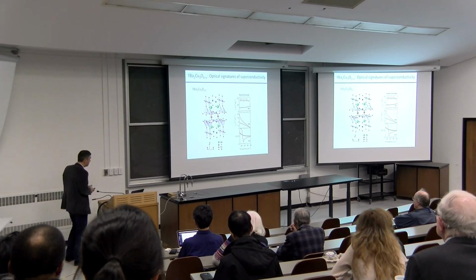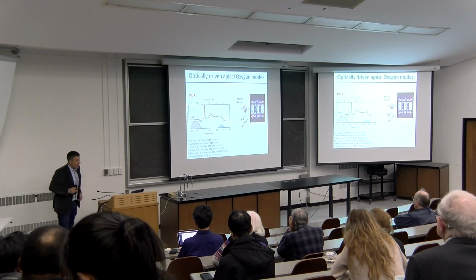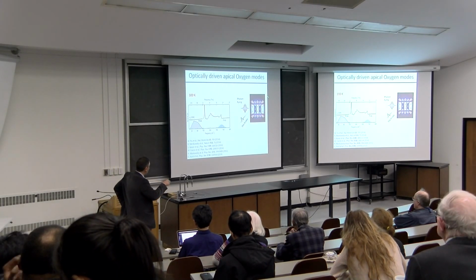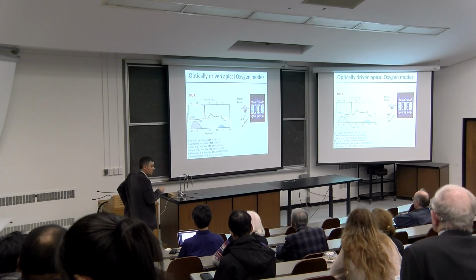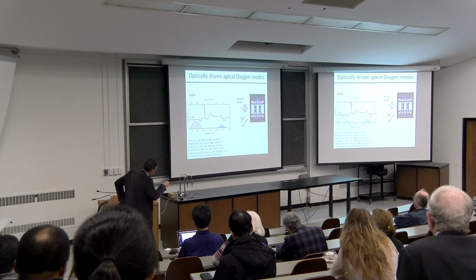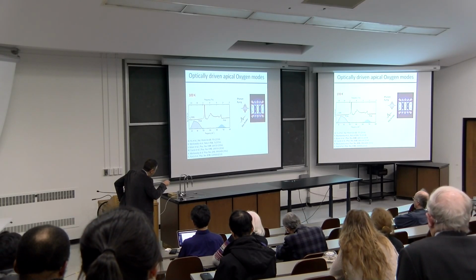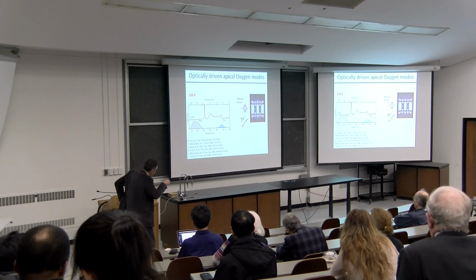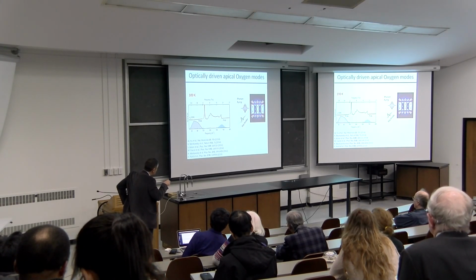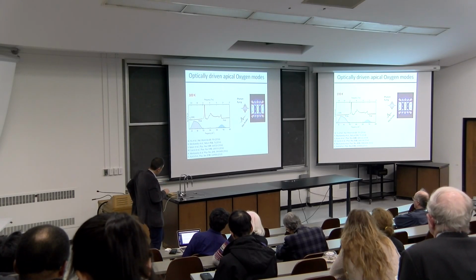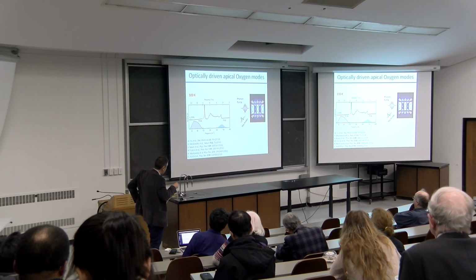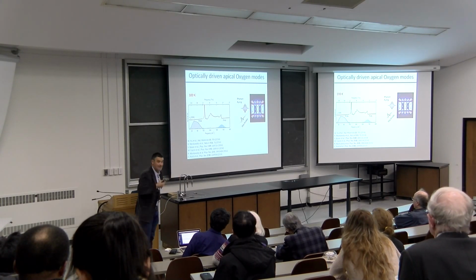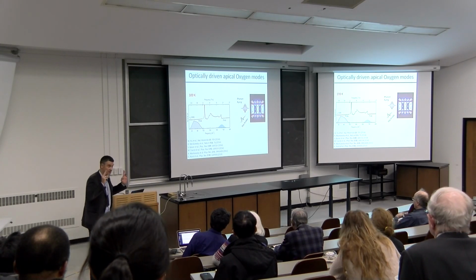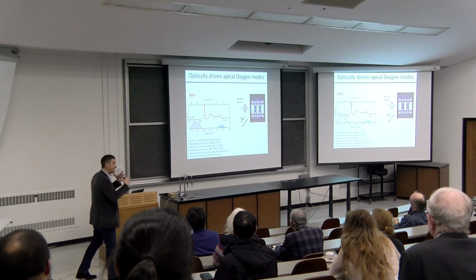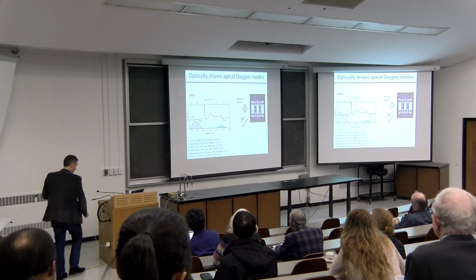So what we would like to do is an experiment in YBCO where we come with a light pulse and drive the appropriate phonon, in which case we're driving these phonons that move the apical oxygen atoms toward and away from the planes. This would be some high frequency excitation. I'm going to use a second terahertz probe pulse to interrogate the properties of the system at the frequencies where I'm expecting these superconducting features to appear. And then I'm going to cross my fingers and hope to see transient superconductivity above TC as long as this phonon is being driven. Okay?